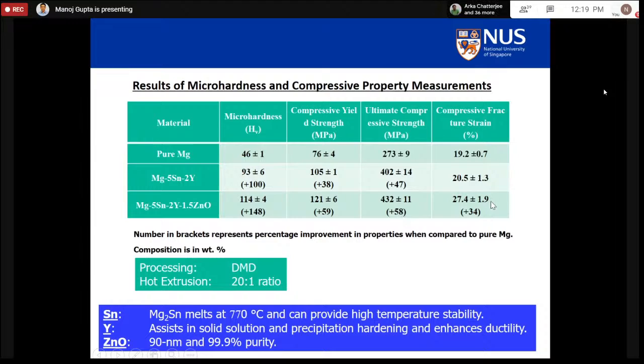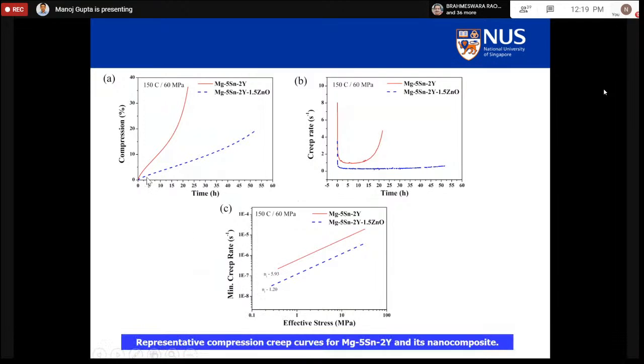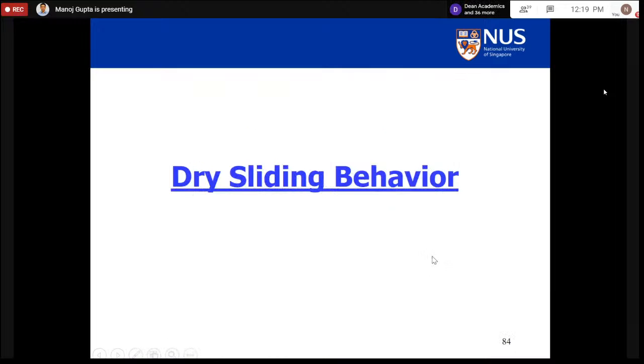And this time you are getting a ductility of 27%, which is superior to most of the aluminum alloys that you are aware of. And apparently, these are also relatively non-toxic elements. And when they did the creep behavior, which is shown by the blue line for the nanocomposite material, it is always superior to the monolithic material. So putting a reinforcement or nano reinforcement improved the high temperature response.